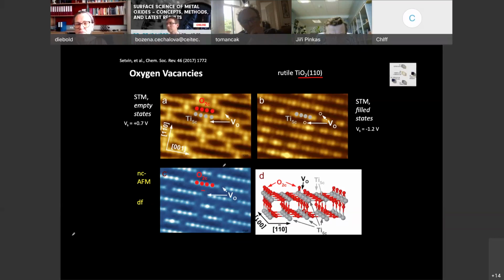Now, it turns out these are very new results, actually. This is from 2017. In the last 4 or 5 years, people have started to use this non-contact AFM on oxides. It's a wonderful technique because you can directly see these oxygen vacancies. For the past 25 years, people have been using scanning tunneling microscopy, so they just looked at the tunneling current.